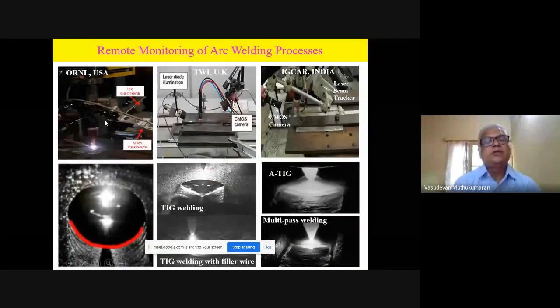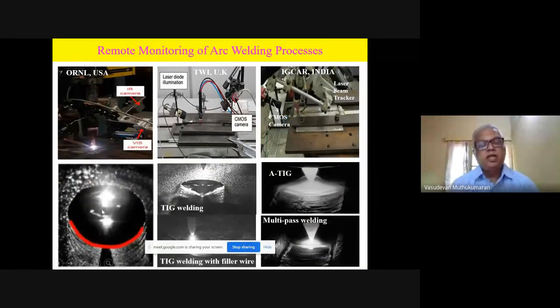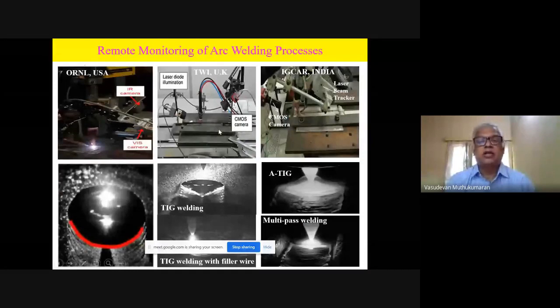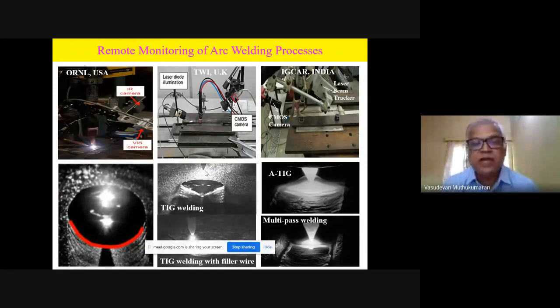They use some cameras to capture the weld pool image at the bottom. The arc is totally not seen. The weld pool appears like a mirror, and you can see the reflections, because they use sophisticated cameras to avoid arc interference. TWI again can use this. They use laser diode for illumination and a CMOS camera for weld pool observation. Again, they could also avoid the arc interference, and the arc effect is nullified.